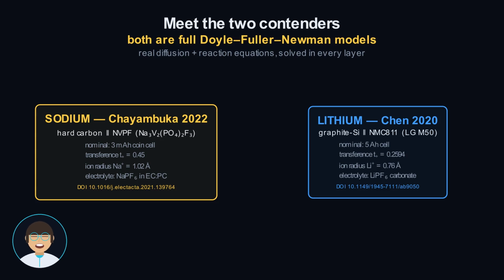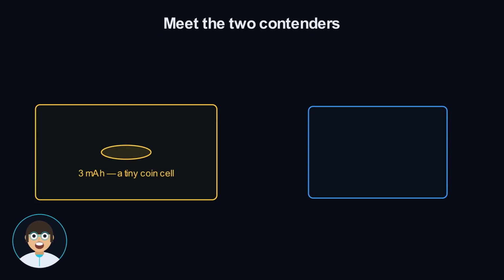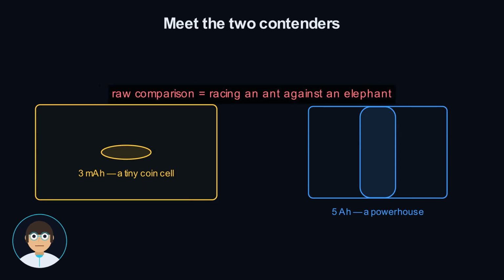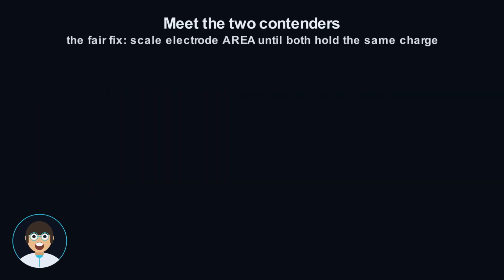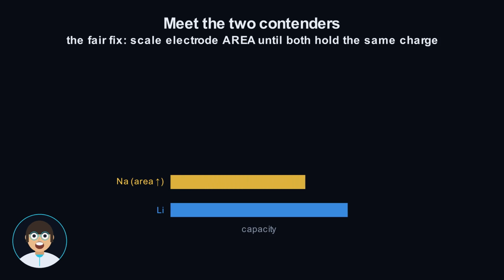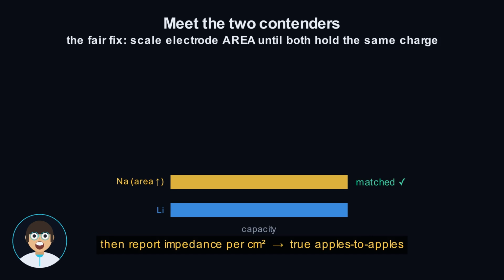But here is the catch, and it matters. The sodium cell is a tiny 3 mAh coin cell. The lithium one is a 5 Ah powerhouse. Comparing their raw impedance would be like racing an ant against an elephant. So we do the fair thing. We hold every internal property fixed, the thicknesses, the particle sizes, the chemistry, and we stretch only the electrode area until both store exactly the same charge. Then we report impedance per square centimeter. Same capacity, same conditions, true apples to apples.